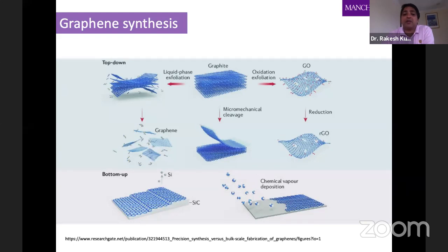You may end up with individual graphene sheets by liquid phase exfoliation, or you may end up with graphene oxide. Graphene oxide is a form of graphene with oxygen functionality around. So you need to reduce the graphene oxide in order to make a pristine graphene, which we call reduced graphene. There's another way for large scale fabrication, which is the bottom-up approach.